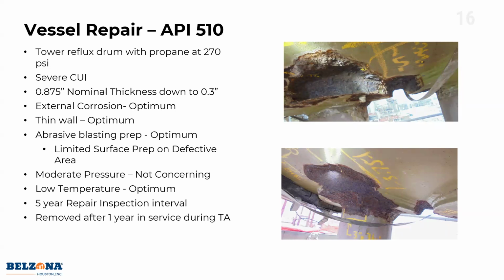Once we blast, we can blast safely without worrying about popping a hole in there. Moderate pressure, so 270 psi, we'd say moderate pressure, not concerning, not like it's a 5,000 psi line or something like that. Low temperature, which is optimum. We gave this a 5-year repair inspection interval. However, we knew going into this they were going to remove it at the next turnaround, which they did. But this allowed everybody to walk around the vessel without a worry that we got a problem here.